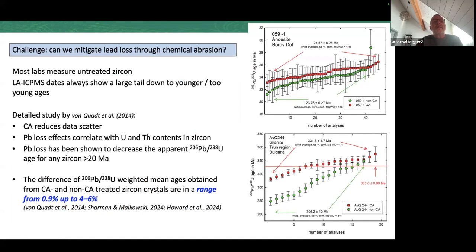So is maybe chemical abrasion the solution to this problem? At least the lead loss we could mitigate through chemical abrasion, because most labs, or 99% of the labs, measure untreated zircons for laser ablation ICPMS dating. And the consequence is that these data always show a large scatter and always have this young tail which goes down to young ages.